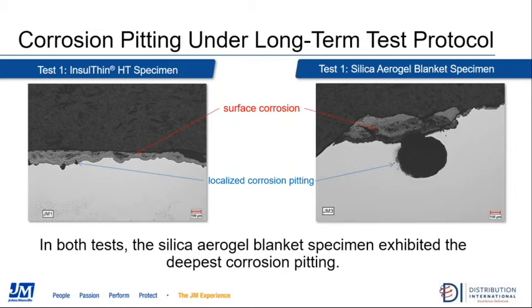So we can look to the right there. This is the Silica aerogel specimen. Again, same thing, that black area to the top is going to be your background noise. The white area at the bottom is going to be the pipe itself. We can see the surface corrosion, and we can see that pit, that localized corrosion extending further into the pipe sample. When I show this to corrosion engineers, they've told me a few times that this right here is what they're concerned about. They're concerned with how far the pits extend into the metal, because this is where the potential for failure arises.